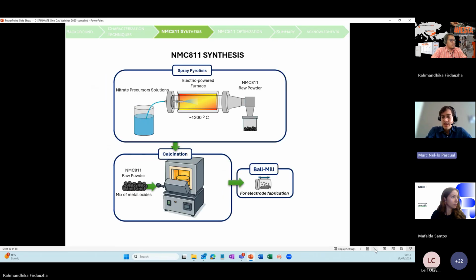So in this case, this powder, as Liv has been mentioning, has been made via spray pyrolysis. I won't be spending too much time on that. But in the end, you are obtaining a raw powder from a nitrate solution, a stoichiometric nitrate solution, and then you need to calcine this raw powder because the right crystallographic structure has not formed yet. There's still a mixture of oxides and carbonates, so you need to do this calcination, and then you also do some processing for the electrode preparation. However, if you look at this schematic representation of the process, we need to look at which points we can act on in order to optimize this material.